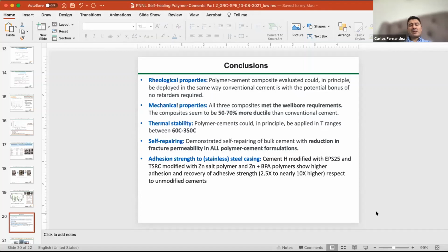But that's something that we haven't done. Having a pressure reactor subject to mineral acid for a year, maybe you end up with a lot of corrosion in the reactor, even if it's Hastelloy or whatever. So the short answer is we don't know. At 30 days, the material is still there. If the polymer at 300 Celsius survives 30 days, I feel pretty good to test it, at least do some